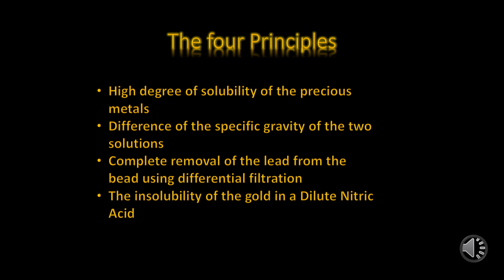The second principle is in regards to the two molten solutions. It is the difference between the solution's densities. The slag density is lower than the lead and therefore will float on top of the molten lead, allowing for the easy separation of the lead bead from the gangue material when it is cooled and solidified.